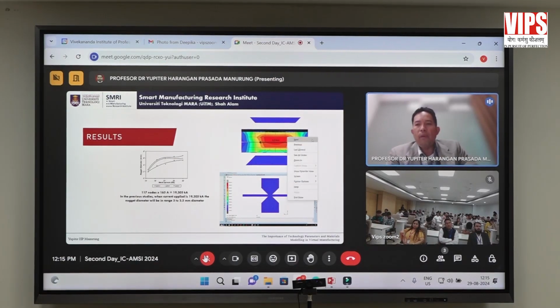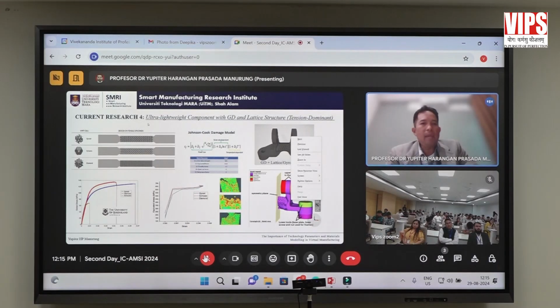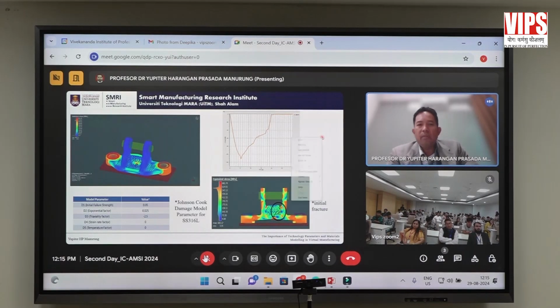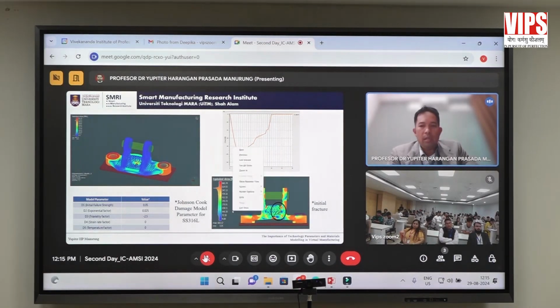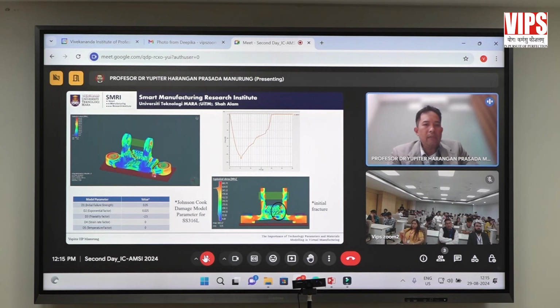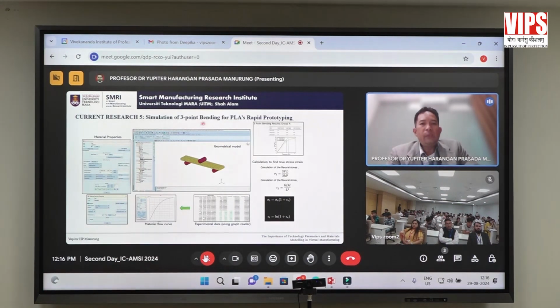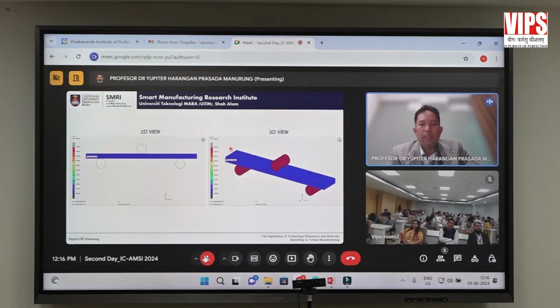Okay, I move faster here because I don't have time. We also do the ultralight component by using lattice structure. We also do the virtual testing here. You see here, we do the virtual testing. We then see later on the cracks, where the cracks are, and so on and so forth, and we compare it. This is for PLA, simulations of the 3-point bending. Also, we do the subroutine and so on and so forth.